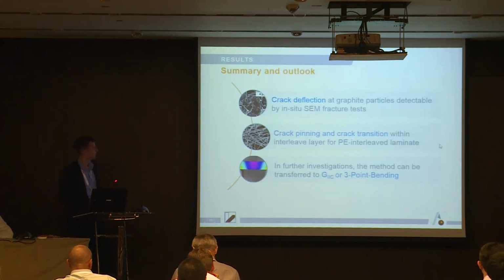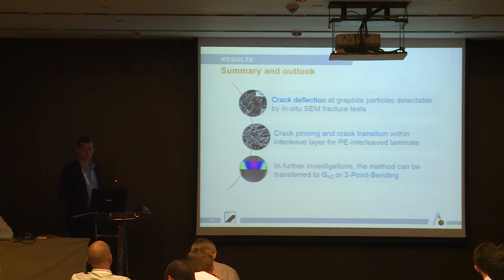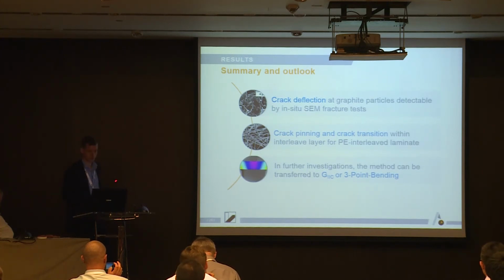So this is already the summary. I know most of you are more familiar with metals, and probably you have an idea how to transfer these results to metals, to metal forms or whatever. I guess there are a lot of possibilities to use this kind of testing device. One can see here in the presentation that the crack deflection with the graphite filled material is detectable by the in situ SEM fracture test. You can see some crack pinning, crack transition with the interleave layered one.